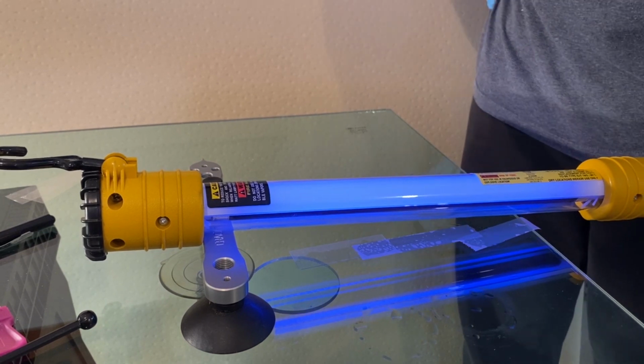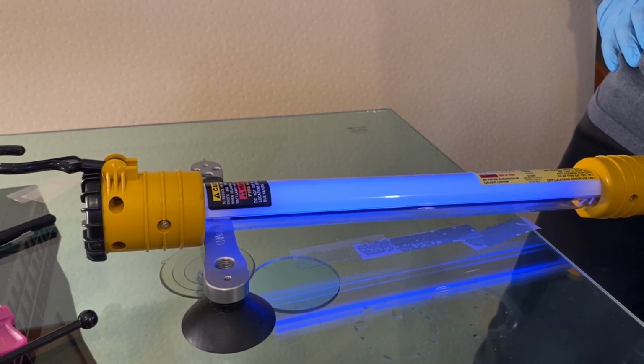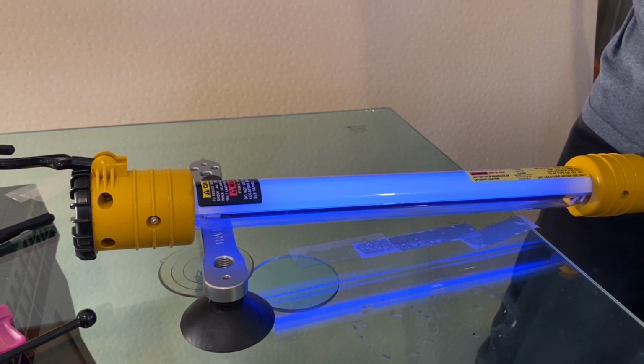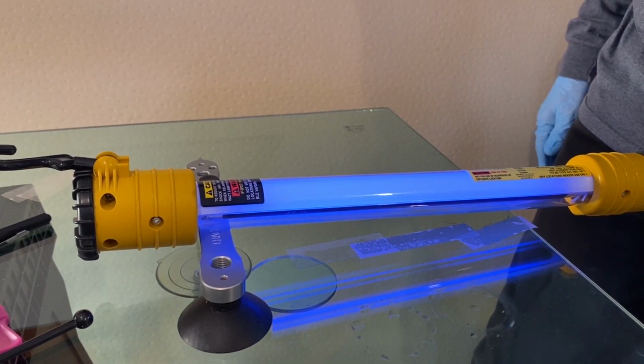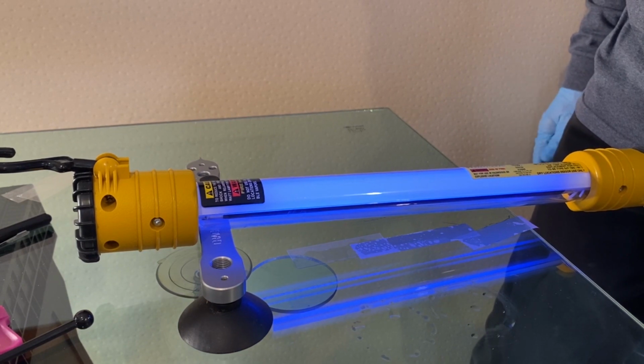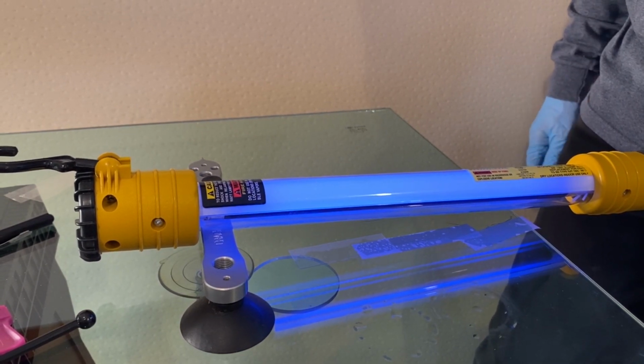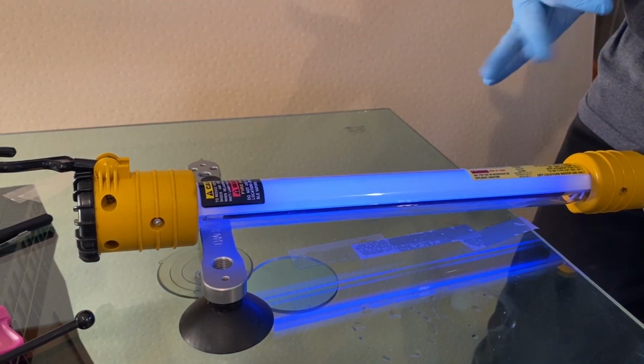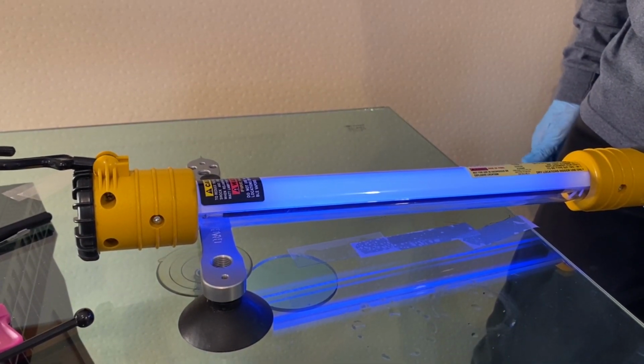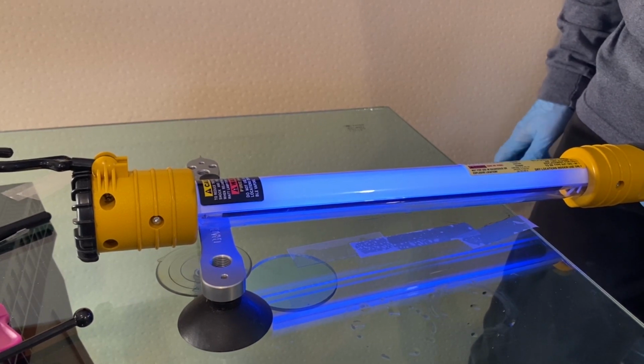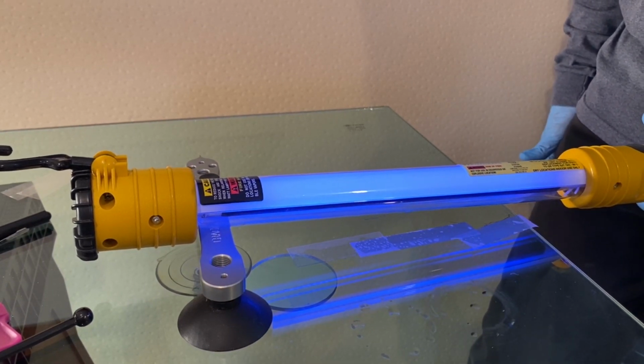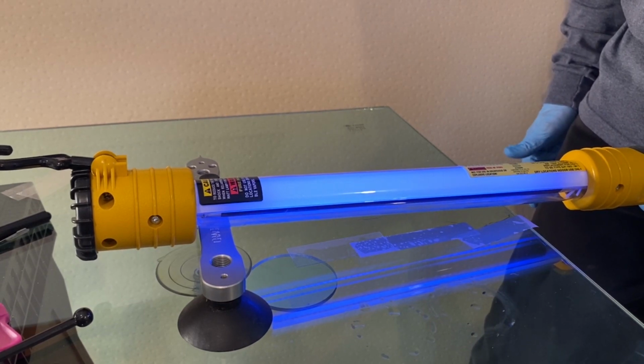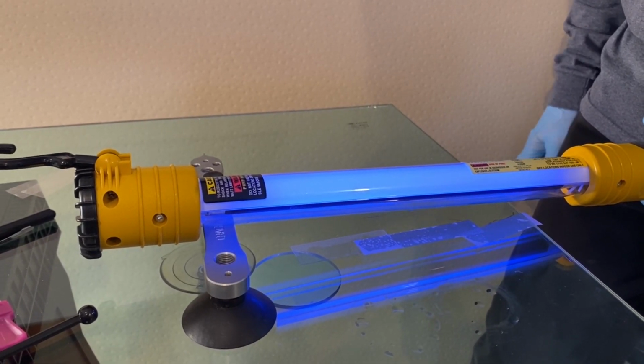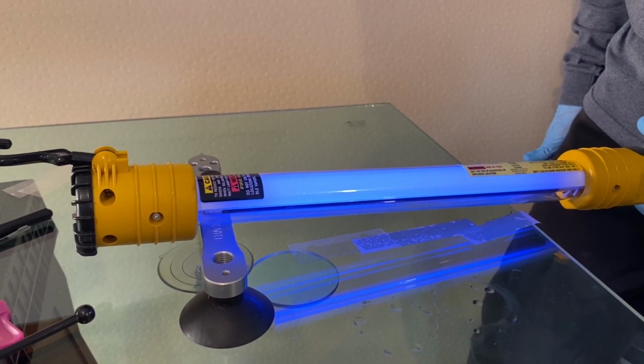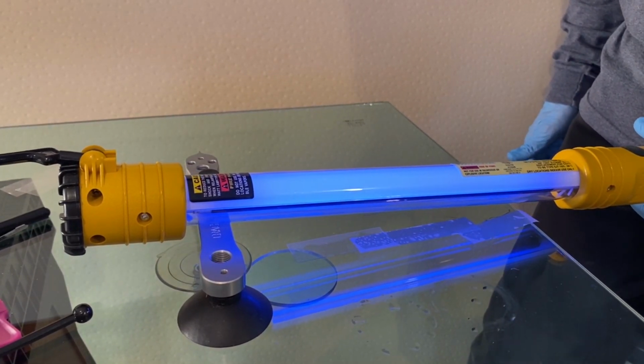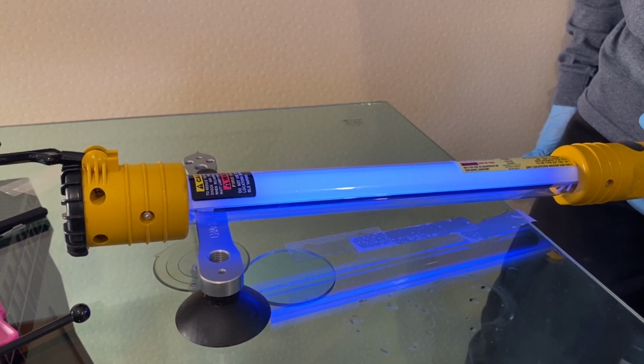The best way to cure, number one, is sunlight. Why sunlight? Because with sunlight, the intensity is perfectly even. So it's going to be a slow cure. A slow cure is much better than a fast cure. If you cure this in 10-15 seconds with strong LED lights, you're going to have broken chain links in your structure, and it is not going to be able to withstand cold temperatures and hot temperatures and thermal resistance. And this is the third most important safety device in the vehicle. It's only going to take you an extra 3 minutes to cure this right.